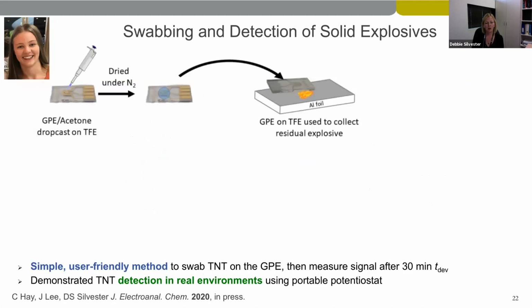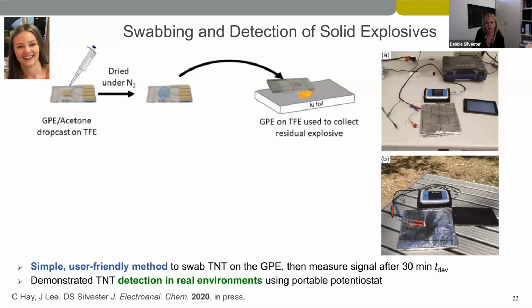And more recently, my PhD student Kathy has been looking at trying to detect solid explosive samples. She tried a number of different methods, but one that was very user-friendly and worked very well was simply using our gel polymer electrolyte, drop cast onto the thin film electrode, drying off the carrier solvent, and then simply turning that electrode device upside down, pressing it several times into the solid sample of TNT. This sample was on aluminium foil to collect the explosive. Then we turn the electrode back over again. We leave it for 30-minute development time, and the TNT then diffuses through the gel polymer to the electrode, and then we can see a signal.